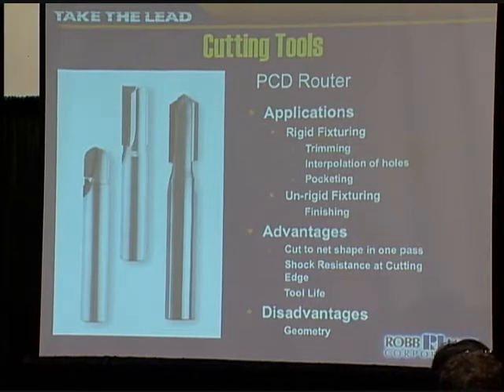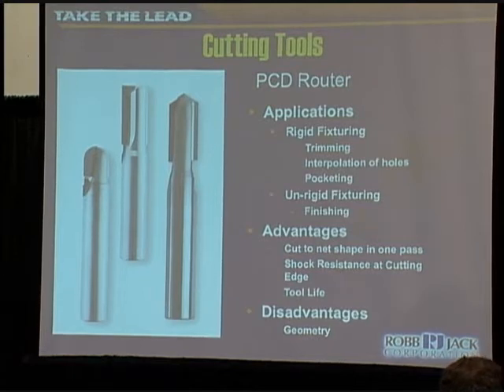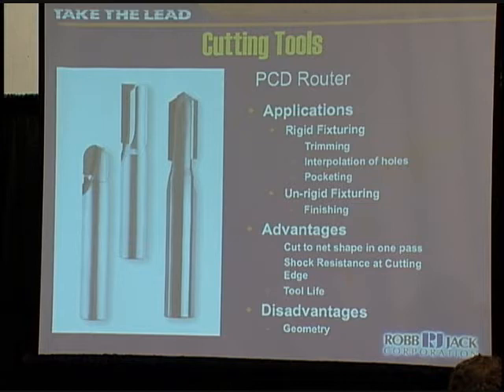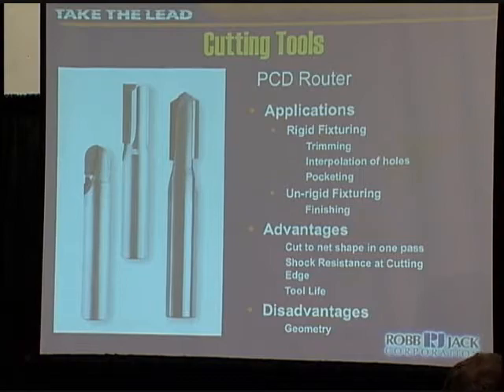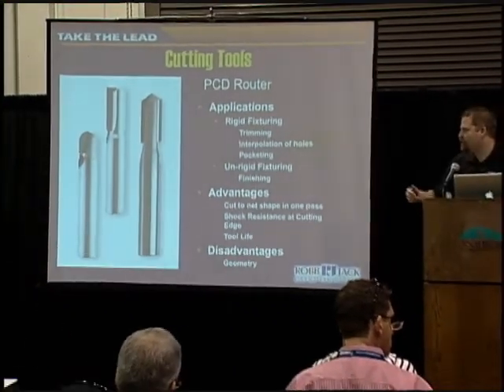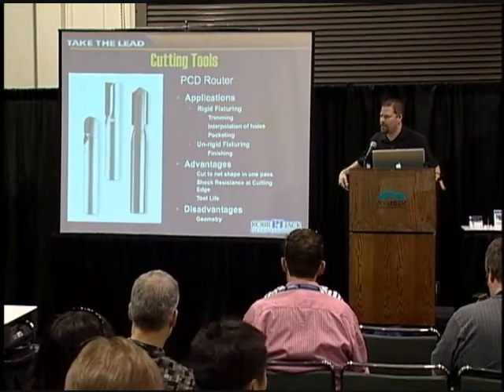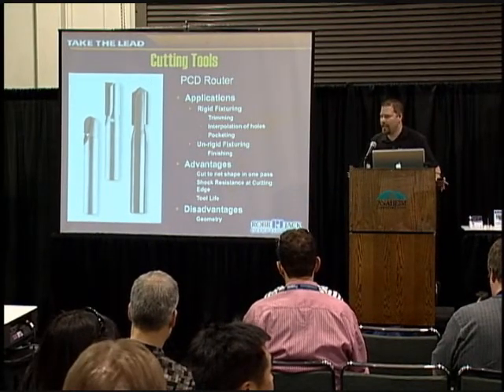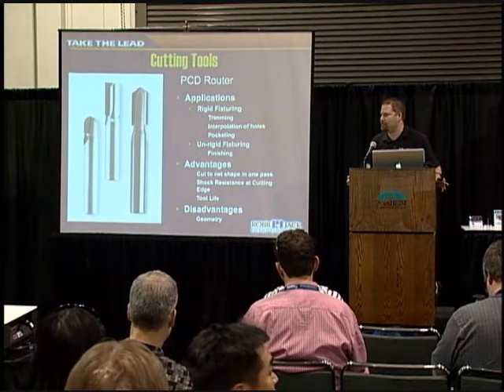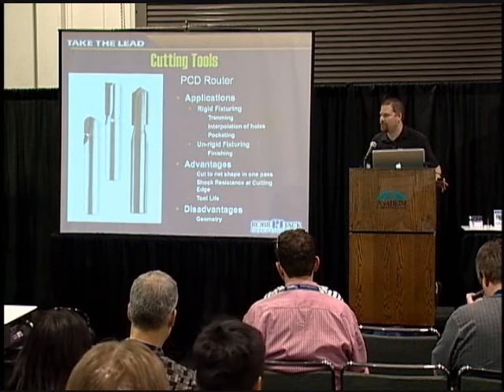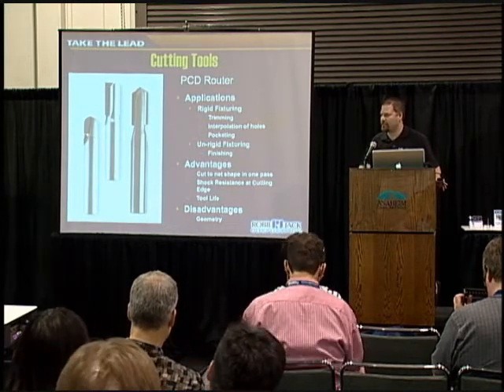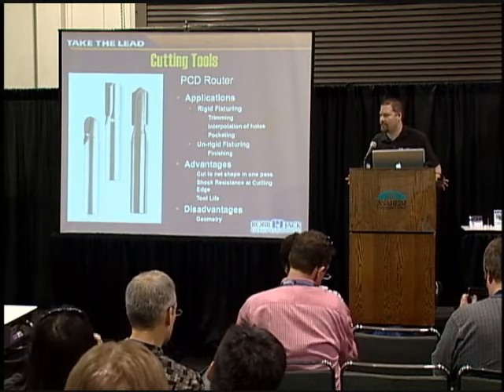The other thing that you're able to do is cut through the part in one pass. When you're working with very abrasive materials like composites, you don't want to rough the parts out, finish the parts, move in a little bit, step down. In a typical application, you can go 1, 2, 3 diameters deep per pass in one single Z pass and machine it right to net shape. You have a tool that's going to hold size. You don't want to double the amount of time it takes to machine the part, as well as double the linear inches, so that you get half the tool life. So you want to go right to net size, machine right to your finished shape, with no hand finishing work required.